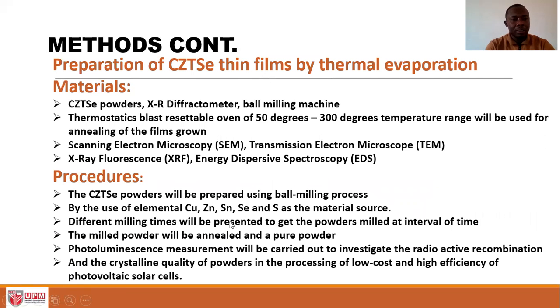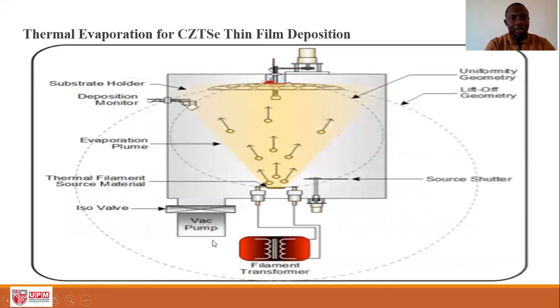Then methods continue. You can see the preparation of CZTSe thin film by thermal evaporation. This time around, we'll be doing the deposition using the thermal evaporation proper. So the materials that will be needed are CZTSe powder, XRD diffractometer, ball milling, and the rest of them. Then procedures. So these are the procedures, and at the end of the day, it's expected to have a higher efficiency CZTSe film that can be used for photovoltaic solar cells. Of course, this is the thermal evaporation machine that we use for the deposition.